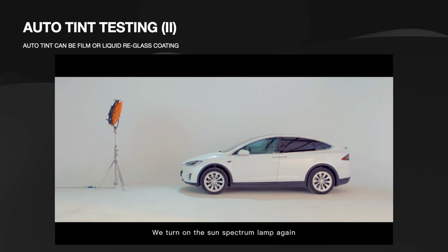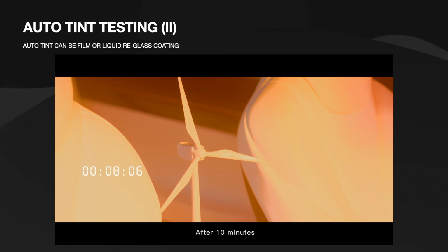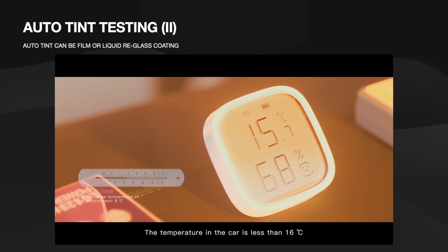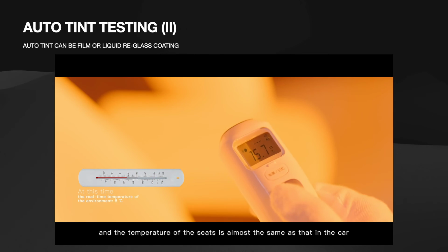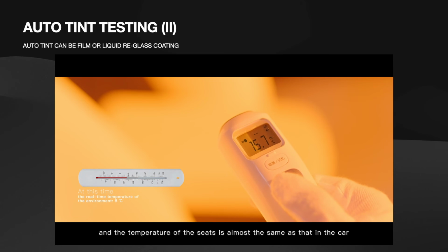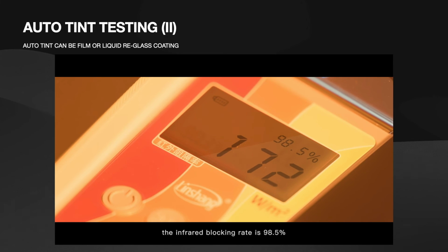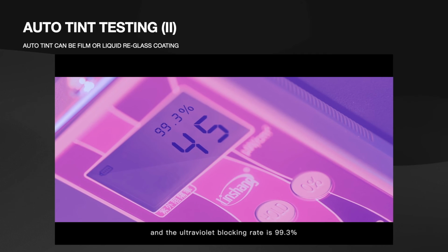We turn on the sun spectrum lamp again. After 10 minutes, the windmill still doesn't rotate. The temperature in the car is less than 16 degrees Celsius, and the temperature of the seats is almost the same as that in the car. At this time, the infrared blocking rate is 98.5%, and the ultraviolet blocking rate is 99.3%.